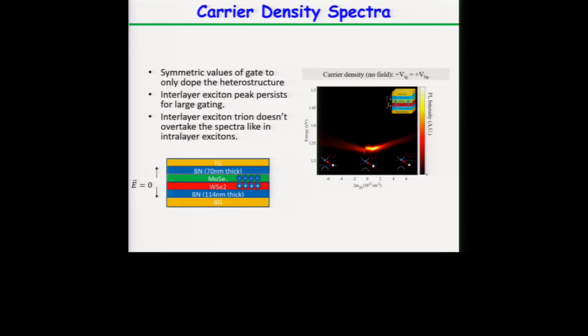We can dope one sample. If we use a positive gate or a negative gate, we can be doping one or the other. What we end up doing is shifting the energy of the interlayer exciton, but it's not shifting much, by about 30 meV. And it's always blue shifting when we add this carrier density onto the sample. As I said, this is probably also due to screening.